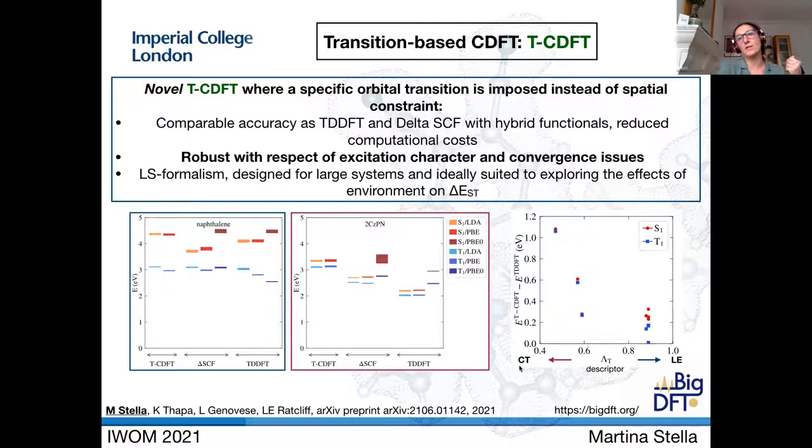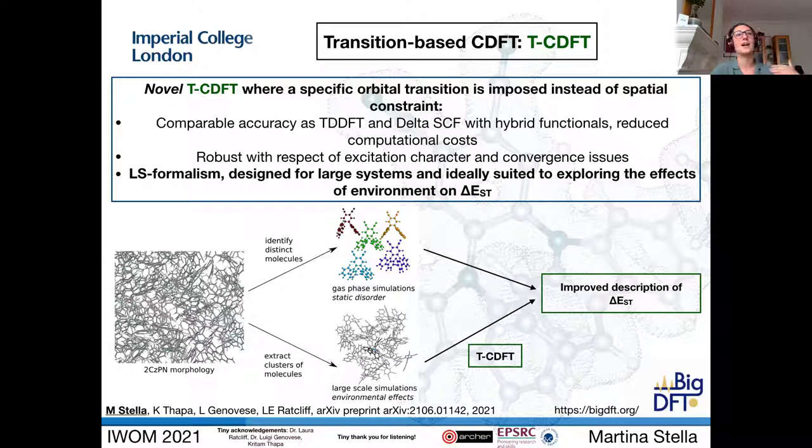TDDFT shows its standard failure with charge transfer excitation with semi-local functional. This confirmed the robustness of our method. Because it's implemented within a linear scaling formalism designed for large systems, it's ideally suited for exploring environment effects on delta EST. We can extract larger clusters to assess the effects on the environment using T-CDFT. Together with information from static disorder investigation, we can improve the description of delta EST. I'm done.